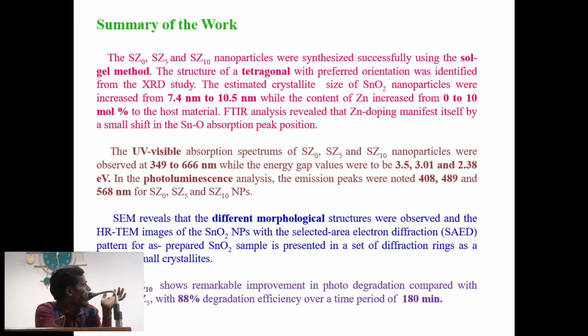So, summary of the work. The rutile tetragonal structures were confirmed in the XRD studies. Then the nanoparticles' crystalline size varied from 7.4 nanometers to 10.5 nanometers across the 0 to 10 molar content in the host materials. And then UV-visible absorption spectrometer, 349 to 666 nanometers in the absorption wavelength. And then PL analysis, 408, 489 and 568 for the pure, 5% and 10% molar content.